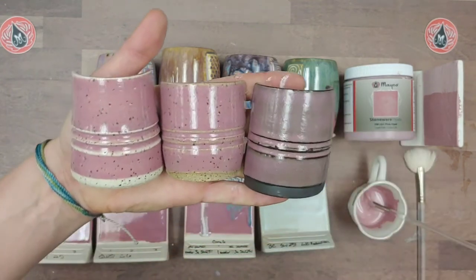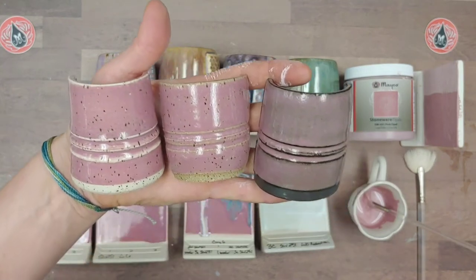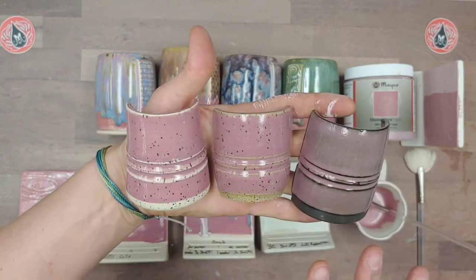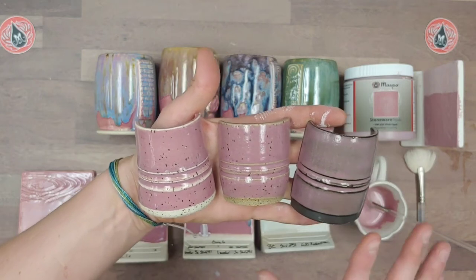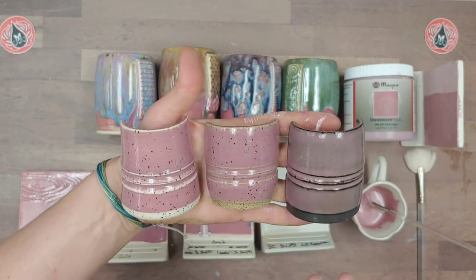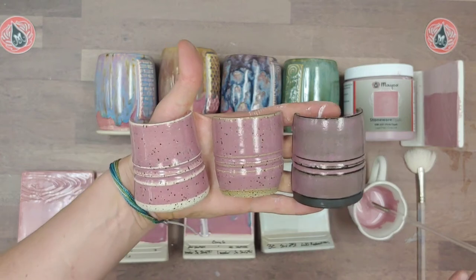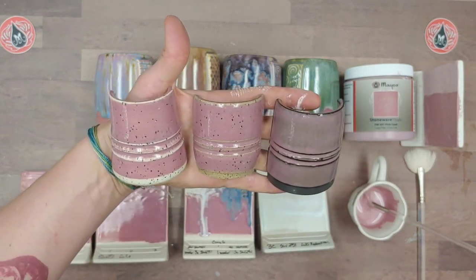Here we have our alternative clay bodies: white speckled, brown speckled, and dark brown, all fired to cone 6 with a drop hold and slow cool. This glaze plays really well with different clay bodies, so the special firing schedule may not always be necessary. But if you have trouble with your surface finish on a clay body, we recommend adding a hold or a slow cool.